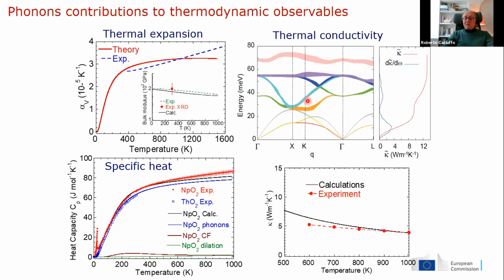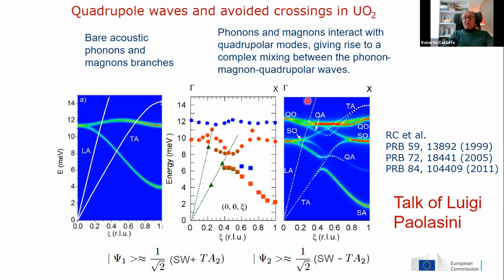Also in the case of uranium dioxide, as you will see in a talk by Luigi Paolasini, inelastic X-ray scattering can be very interesting because it provides information complementary to what you can observe with neutrons. For instance, in the case of uranium dioxide, what you would expect is a continuous phonon dispersion and only 2 magnetic branches, even in presence of anisotropic superexchange interaction, but with just 1 optical spin wave branch and 1 acoustic. The 2 branches should be degenerate at the zone center, and have the same energy at the zone center and at the zone boundary.